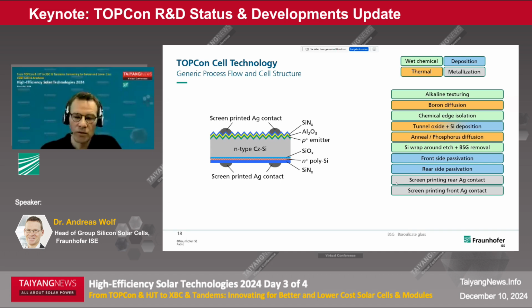Printing is done in 2 steps per side, usually with floating bus bars or even latest developments with a zero bus bar approach. Then contact firing forms the contacts. After this, usually a post anneal is performed, with temperature and illumination, which facilitates the hydrogen diffusion into the bulk and increases fill factor and VOC.